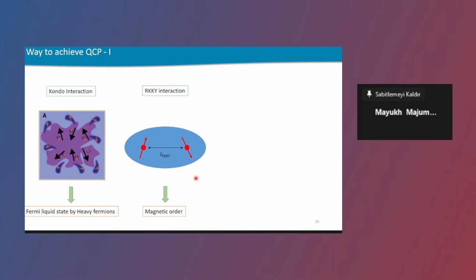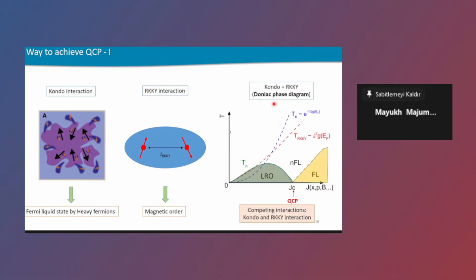And indeed, there is a quite well-known phase diagram proposed by Doniach. Here along the x-axis, this is nothing but the exchange. It can be the RKKY type of exchange, it can be the Kondo type of exchange. And along the y-axis, you have the temperature scale. While J is rather small, the Kondo temperature is subdominant, and is not able to dominate over the RKKY interactions. As a result, when J is small, you would expect a long-range magnetic order. On the contrary, if you increase the J value, then the Kondo temperature or Kondo energy scale increases and dominates over the RKKY type of exchange interaction.